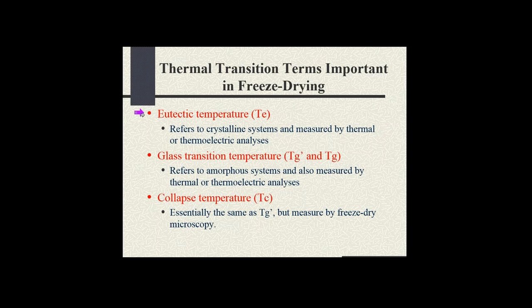Now, we have to stay below these temperatures. If we exceed the eutectic melting temperature or the glass transition temperature, Tg', that interstitial space is going to be a fluid. Now, the problem is, in primary drying, the main goal is to remove the ice in the ice channels. Well, if the interstitial space is not a solid, it's not going to support its own weight, and it goes through a collapsing event. So essentially, you end up with a puddle of goo in the bottom of the vial.